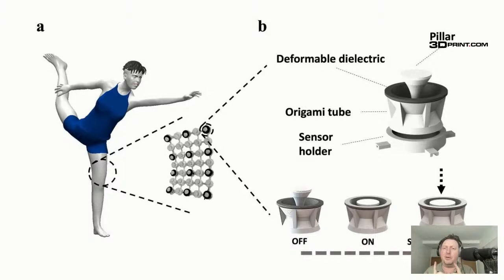So they've used a dual IDEX material extrusion printer, a Vivedino called the T-Rex 3.0. I'd never heard of it. It's a dual nozzle printer, about $1,800 or something like that. They've used NinjaTek filaments, two different ones: the NinjaTek Cheetah, which is 95A Shore hardness, and the NinjaTek Eel, which is 90A Shore hardness. I like this so much already because it's using a relatively affordable printer and filaments we can all get.